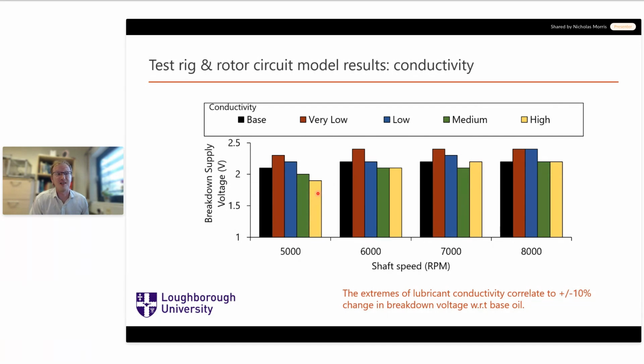It marginally changes. So what I think we can say here is that the extremes, which is possible in terms of current lubricant additive pack conductivity, correlate to, and it's correlate, not necessarily causes, a plus or minus 10% change in breakdown voltage with respect to the base oil. And this is probably more likely to be as a result of not the conductivity and dissipative current leakage, but more likely a change in the dielectric strength of the film based on adsorbed layers on the surface relating to the additive pack chemistry.